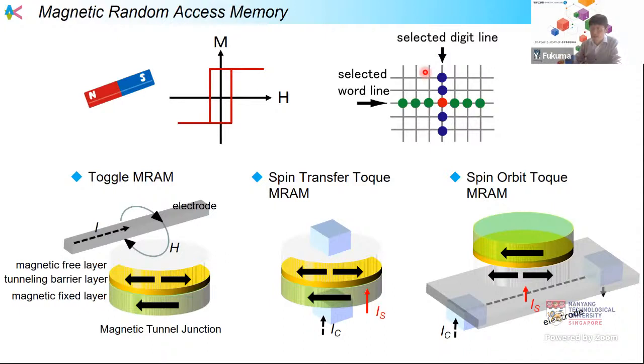When we apply current into this bit line or word line, we can generate a magnetic field along the wire. Then we can switch the magnetization state in the free layer. For the reading part, we can use a magnetic tunnel junction. The resistance state changes according to the magnetization configuration between the free layer and the fixed layer. In the parallel state, it shows a lower resistance state, and in the anti-parallel state, it shows a higher resistance state.